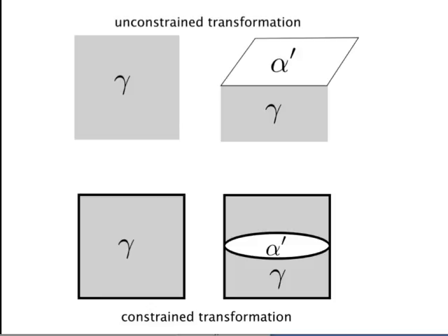Now, the reason why they're in the form of thin plates, and we'll do this quantitatively in a short time, is because there is constraint from surrounding material. And martensitic transformation involves deformation. So to minimize the strain energy due to that deformation, it adopts a thin plate shape, and we'll see why later on. But supposing you only have a single crystal and it's surrounded by air, then basically there's nothing to resist the formation of martensite, and we will simply pick up the deformation due to martensite. It won't be in the form of a thin plate.